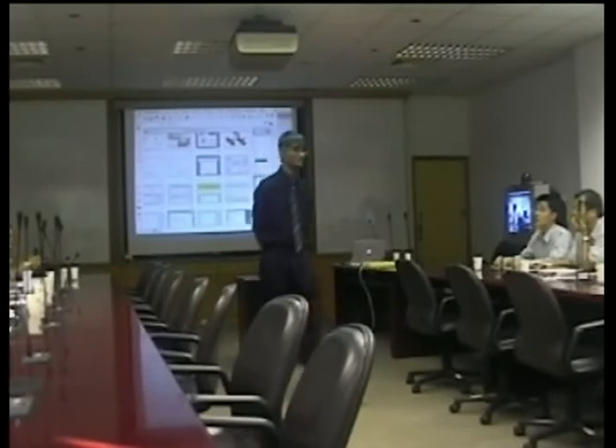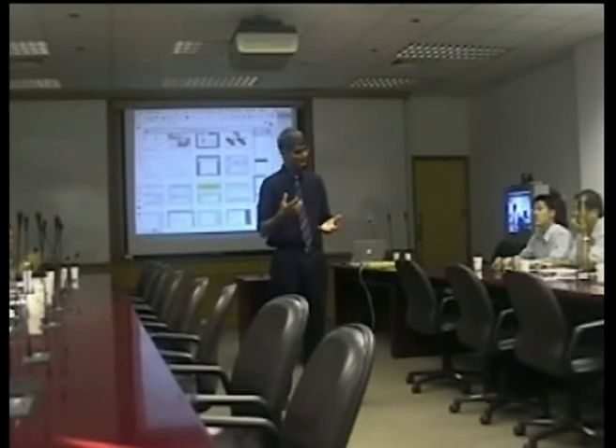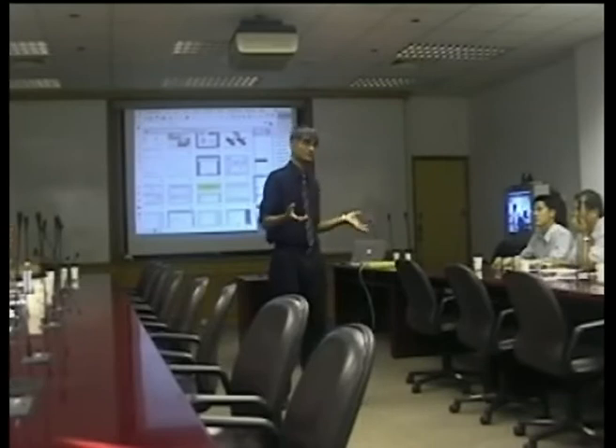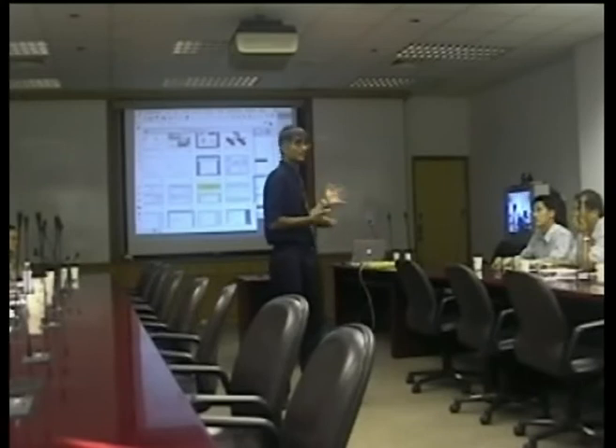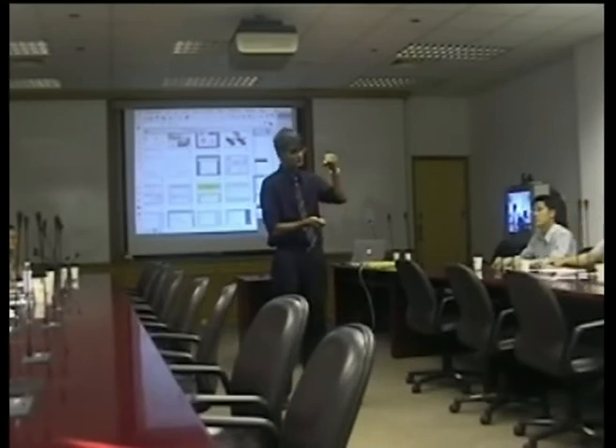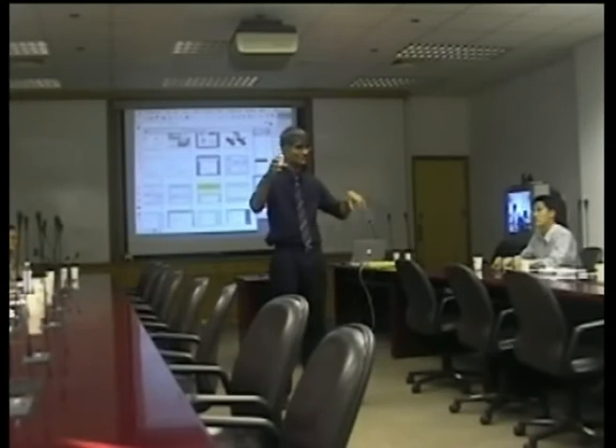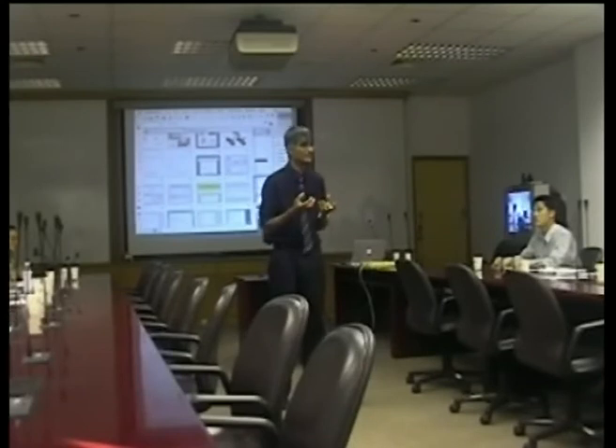What happened was the stainless steel wire. It brought back a lot of memories. So what we want to do, always, is to look at the entire set of evidence and look at the differences between, say, stainless steel and non-stainless steel. Over there, we start with two phases which are mixed up, and it's a process which is favored by thermodynamics, because take high carbon martensite and low carbon ferrite: if you produce an average composition, you actually get a reduction in free energy, which was very surprising. It's not surprising after we've done the calculation, but it was surprising before.